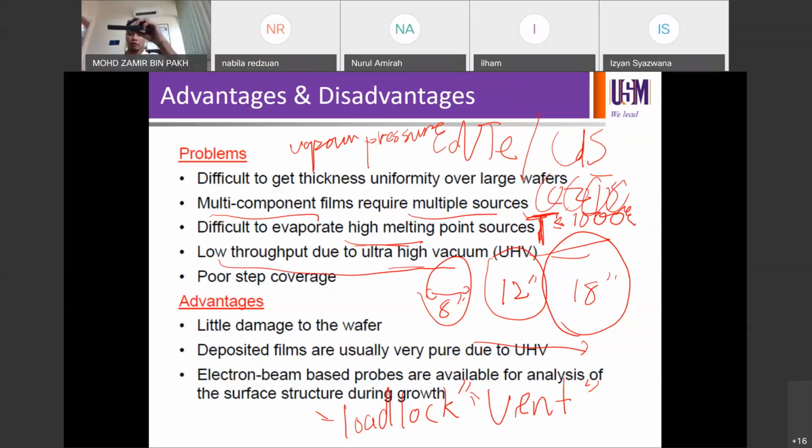So you use the load lock, vent the load lock. Once it has vented, it is now equal to atmospheric pressure, so you can open, remove your sample, close it back, or put your next sample, and evacuate it down to -7. Then when this chamber's pressure matches the other's pressure, you open the valve here, put in the sample, close the valve, do the processing, then remove it when finished. Done. So the load lock is an invention. It's a good invention to eliminate this problem.